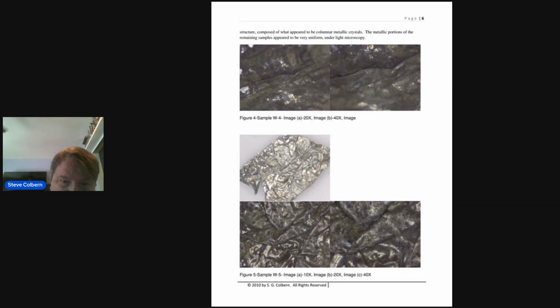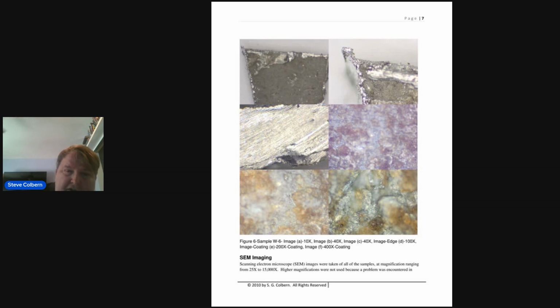Yeah, this sample is very crumpled, W5. Mr. Anderson said that W5 and W1 might have been identical, but the analysis results, I believe, are also very similar. Next page. Here's the sample W6. There's the layered structure that I mentioned, and this sample, in my opinion, definitely had a coating that was applied. You can see that in the bottom two pictures. It was bonded pretty well to the metal, and it just has the appearance to me of a sample that was made by chemical vapor deposition or some other technique along those lines. After this, we did the SEM testing.